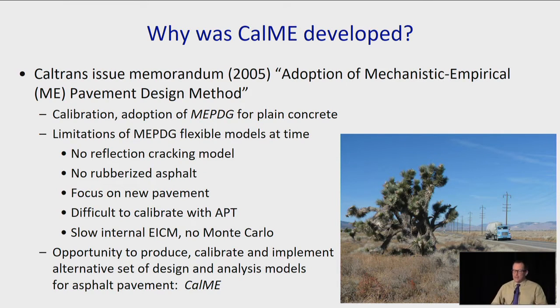We felt at the time that the MEPDG seemed to have no reflection cracking model, focused primarily on new pavement design. We had an APT program at the time, and we wanted to be able to use our APT program to calibrate the model, so we needed an approach other than Miner's Law to be able to calibrate using our APT data. And we were finding a lot of issues at the time with the software, which have been resolved in the meanwhile, but we definitely had some thoughts about reliability that we wanted to look at,